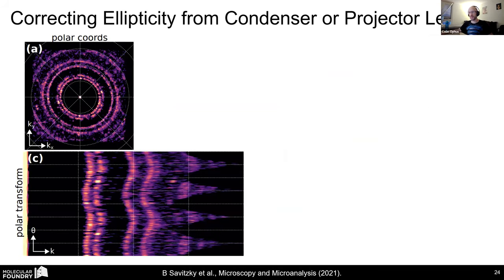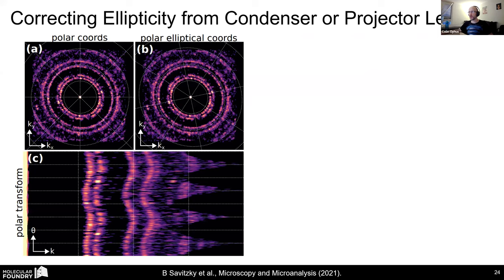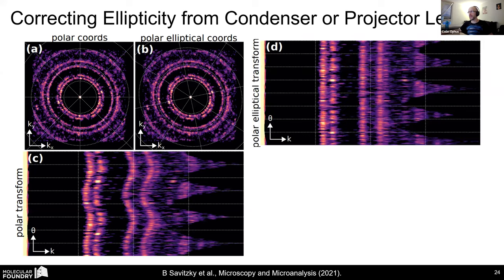I mentioned amorphous materials. One of the things we have to do in our experiments is calibrate ellipticity. It's very difficult to align the diffraction patterns perfectly on the optic axis. And if you're misaligned in the condenser projector system, and then you take a polar transform of your data, you can see these characteristic wavy lines here. And this is because of the elliptic distortion. So we have codes to fit this ellipticity and then be able to do a polar elliptical transform and recover the diffracted spot scattering vectors with much, much higher precision.